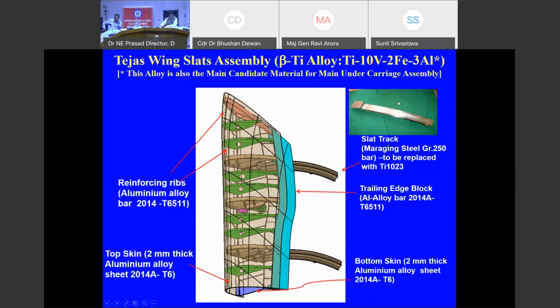So we were able to get thin sections like this from the beta titanium alloys, qualified now aeronautically, and this is the only beta titanium alloy which can replace maraging steel one-to-one in terms of specific strength and still retain much more advantage in terms of specific modulus, as well as allow the slightly higher thickness sections, which is not possible for a high strength alloy like maraging steel. But it has extremely good corrosion and erosion resistance. That is an added advantage. So landing gears which were made earlier from maraging steel are replaced with beta titanium, and the LCA2 will have landing gears from this alloy.